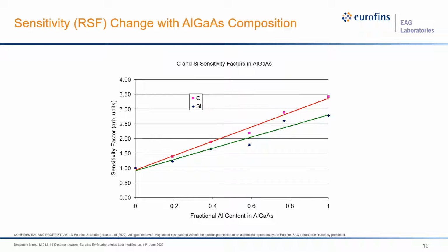We devised PCOR-SIMS analytical functions by analyzing known amounts of dopants and impurities in a series of aluminum gallium arsenide materials ranging from gallium arsenide to aluminum arsenide. This shows how the sensitivities for carbon and silicon, the most often used P and N-type dopants in VCSELs, vary with aluminum composition. The difference in sensitivity can be as much as a factor of 3.